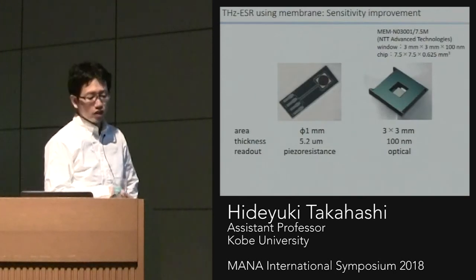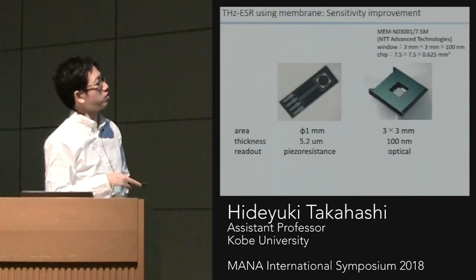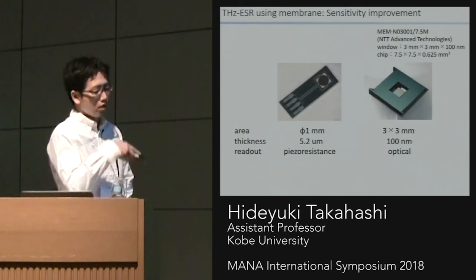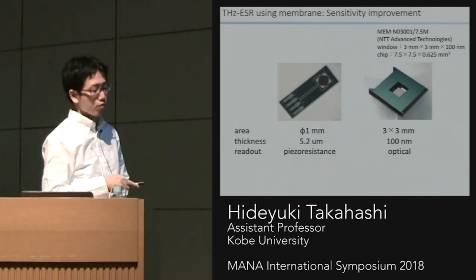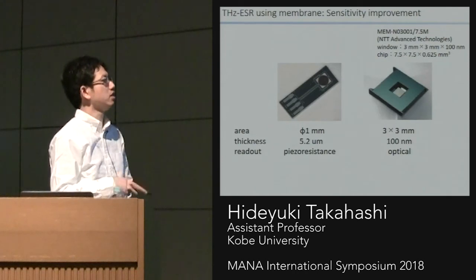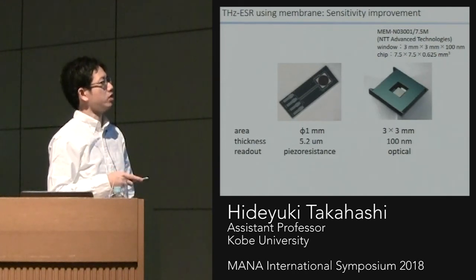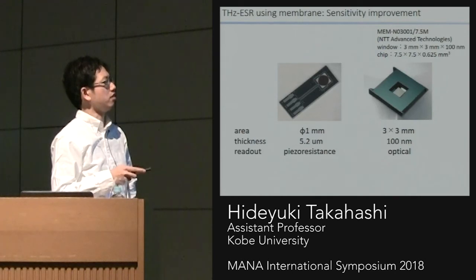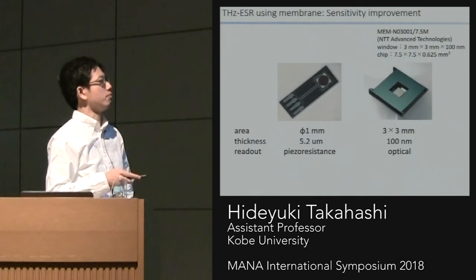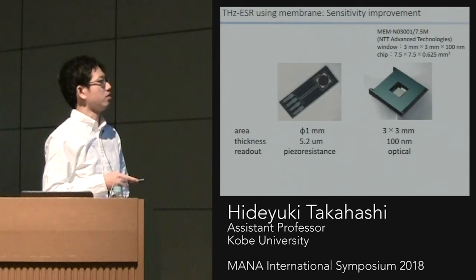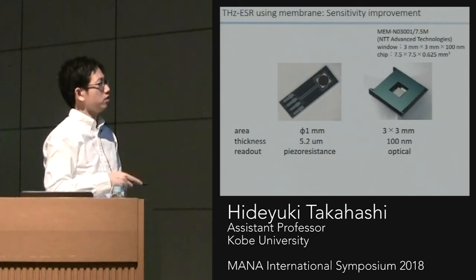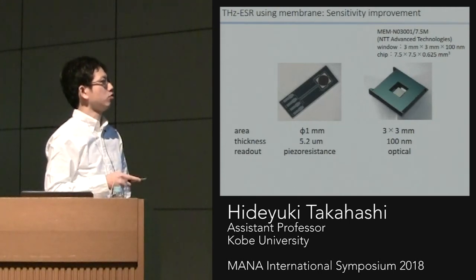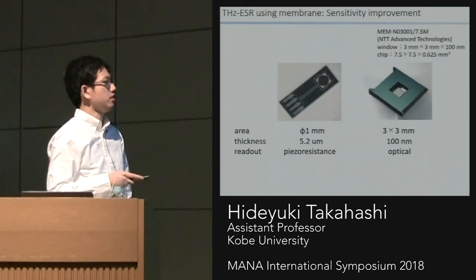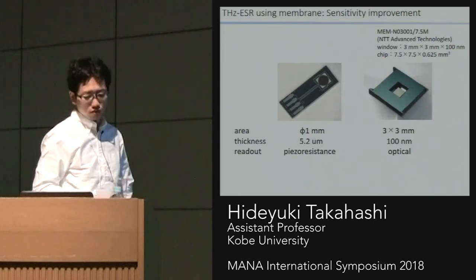And finally, I want to briefly show the more recent experiment. After the MEMS, we started to use a much thinner membrane. This is also a commercially available membrane, but the material is a little different. This is a silicon nitride membrane. The thickness is much thinner, 100 nanometers. Although this chip has a piezoresistive readout, in this chip the piezoresistive circuit is not embedded, so we need the optical detection method.